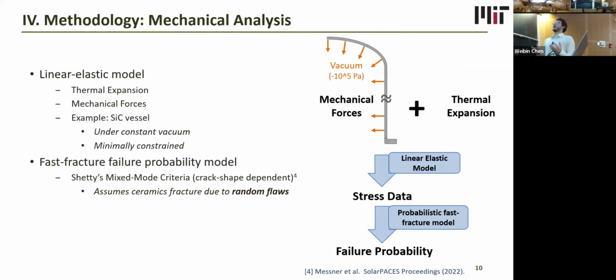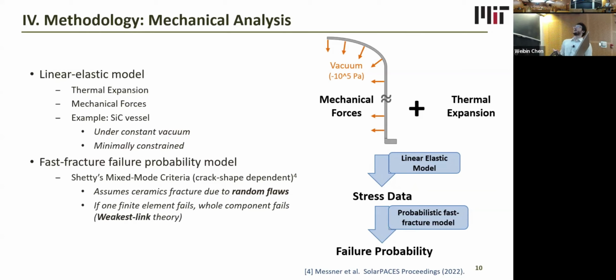Instead, ceramics really fracture due to random flaws distributed throughout the material, and it's dependent on the size of the component as well. So to model this, I use something called the Shetty's mixed mode criteria model, which is a crack shape dependent model. It basically calculates the probability of failure for each finite element and then combines them all, assuming that if one finite element fails, the entire component will fail because of the weakest link theory approximation for structural ceramics. We use the stress field at the time of maximum tensile stress because ceramics are weaker in tension than they are in compression.